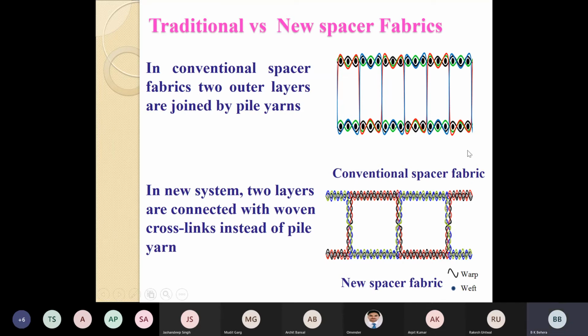So when these spacer fabrics are converted to composite material, a composite made with simply one supporting thread versus one supporting fabric, rather two supporting fabrics, we will have significant difference in their mechanical performance, particularly with respect to load bearing capacity, compression energy, energy absorption capacity, ability to sustain impact load or ability to sustain compressive load.